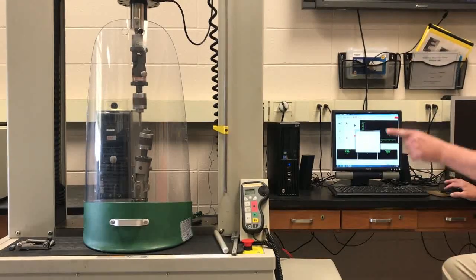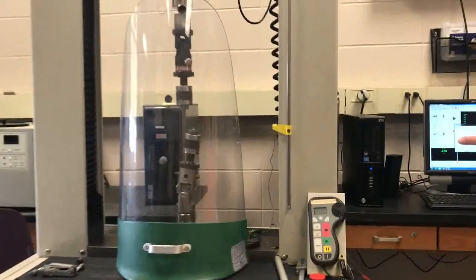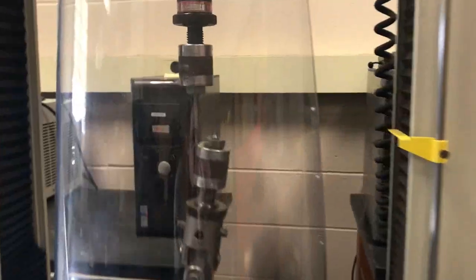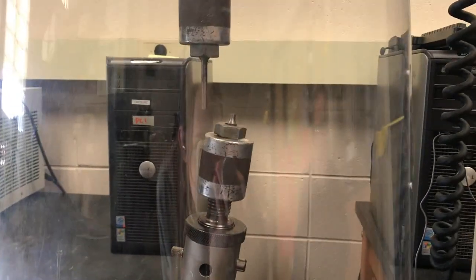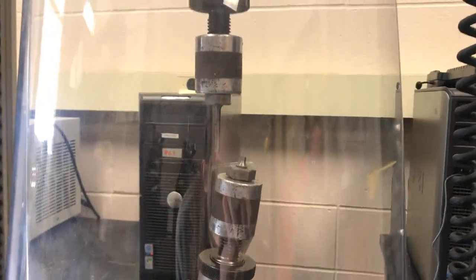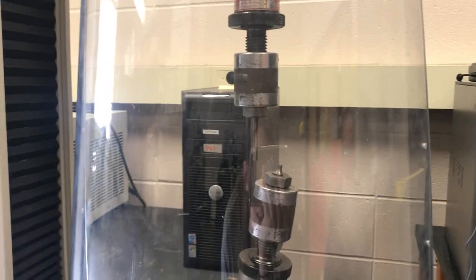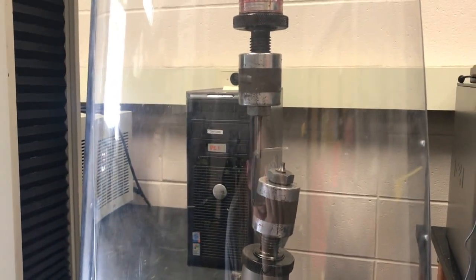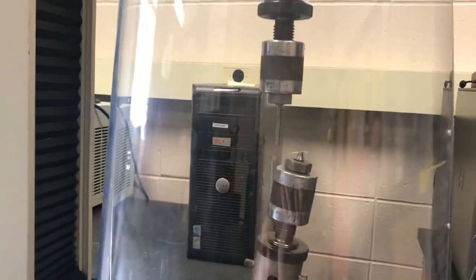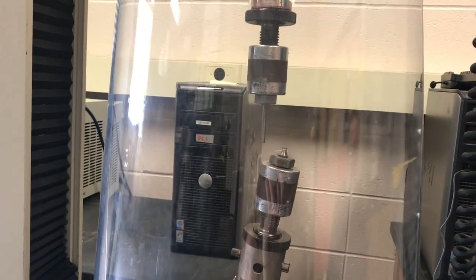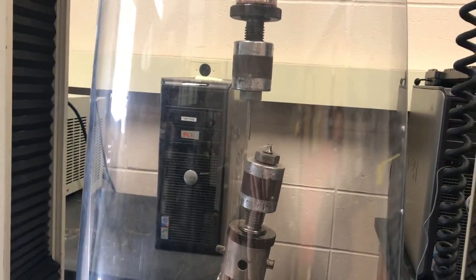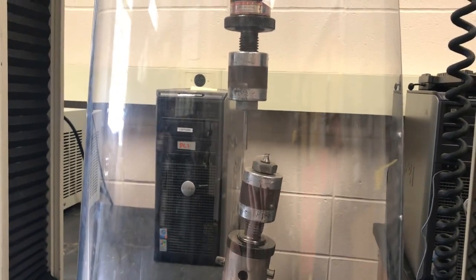So you can see that the sample failed in the test region as we planned. Then it broke pretty cleanly, which is normal for this type of sample, steel. So I think we have a good result.